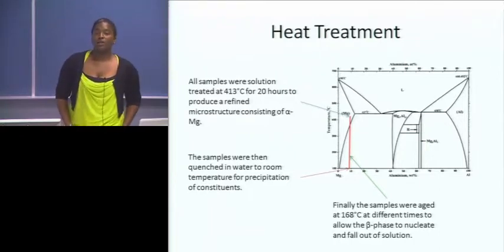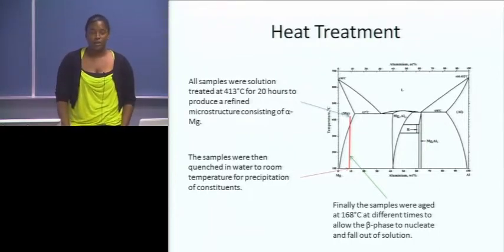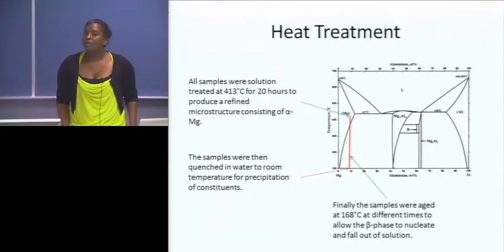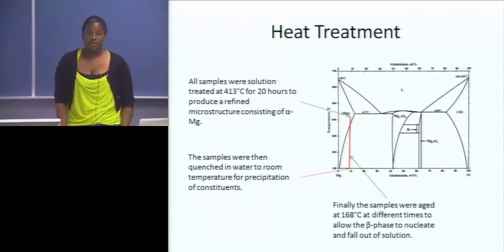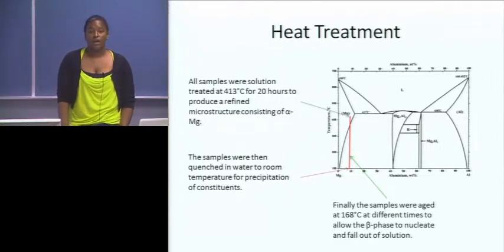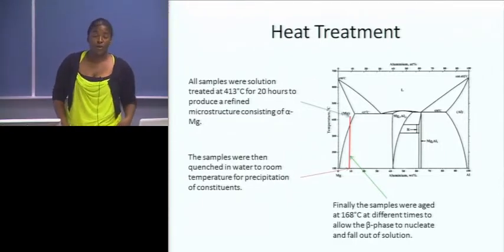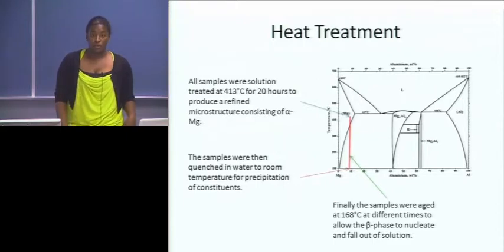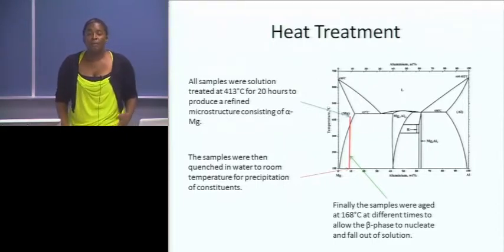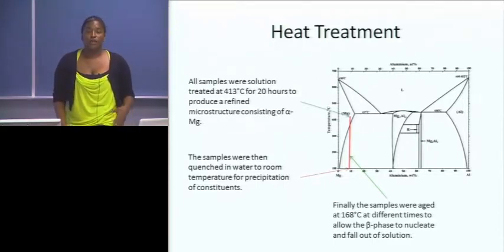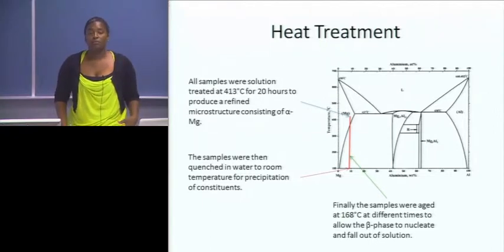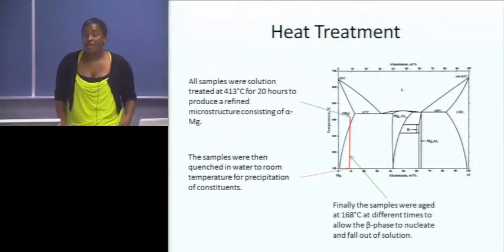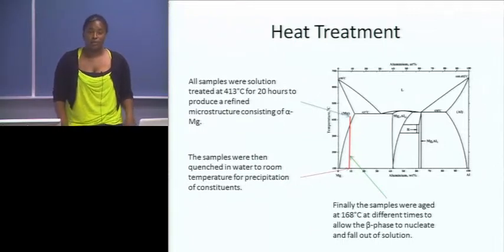AZ91 is a magnesium alloy consisting of 9% aluminum and 1% zinc. Most recently, magnesium alloys have received a lot of attention because they're lightweight. They have the potential to have a high strength to weight ratio. They have a low density, which is about 2/3 that of aluminum, but they still have some disadvantages as far as the strength is not as strong as materials that are currently being used in industry today. They have a low corrosion resistance and burn resistance.